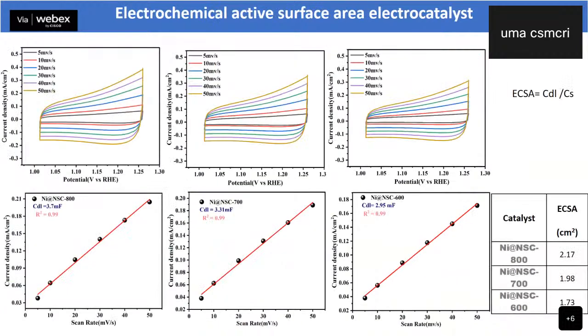The electrochemical active surface area is calculated by performing the CV at different scan rates from 5 millivolt per second to 50 millivolt per second, and the CDL value is calculated from a non-faradaic region. On the basis of CDL value, electrochemical active surfaces are calculated and found that the nickel 800 has more active surface as compared to nickel 700 and 600.